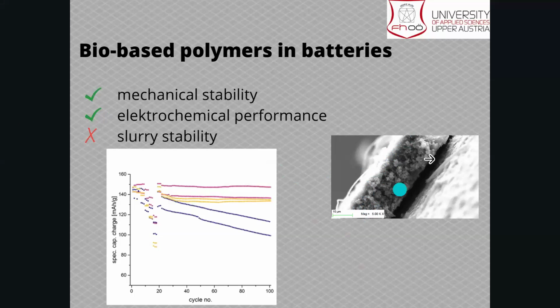We also prepared some electrodes out of the sodium alginate mixture. What we found out was that they do have a good mechanical stability, concerning bending and peeling tests, for example. They also do have a very good electrochemical performance. We can see here on the left, there was one really working badly, and the other examples really performed well, also over a little high amount of cycles of around about 100 cycles.